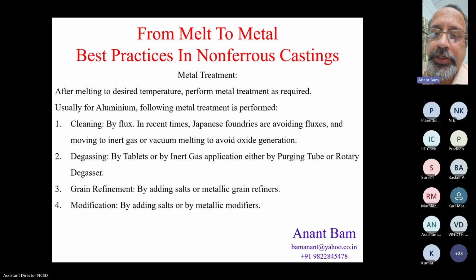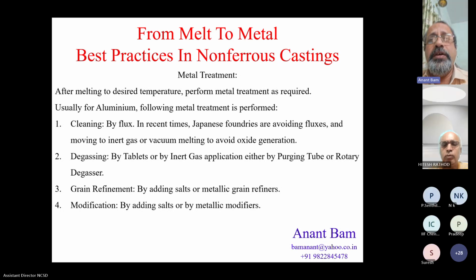Because either the ingots or the input material itself is dirty, or there is freshly created aluminum oxide during the melting process itself. Hence, we have to clean that oxide. We have to separate that oxide from the metal by applying cleaning fluxes. So if the metal is clean initially, do we really need to clean it? Again, the answer is no. So the Japanese have moved ahead and avoided fluxes by way of vacuum or inert gas melting.